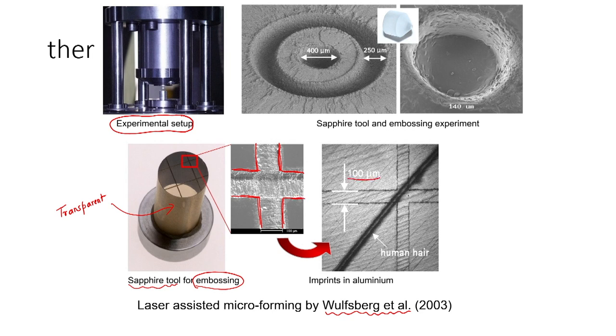You can just imagine, we can easily get about a 100 micrometer channel or feature, which is a little larger than the human hair. These imprints have been made on the aluminium work part. In a similar way, we can also emboss a complex shape. Just look at this complex shape; the dimensions are in microns. This is a cavity of around 400 micron, and an annular depression with a width of about 250 micron. Moreover, another cavity, about 140 micron, can be easily generated by using this laser assisted micro forming operation.